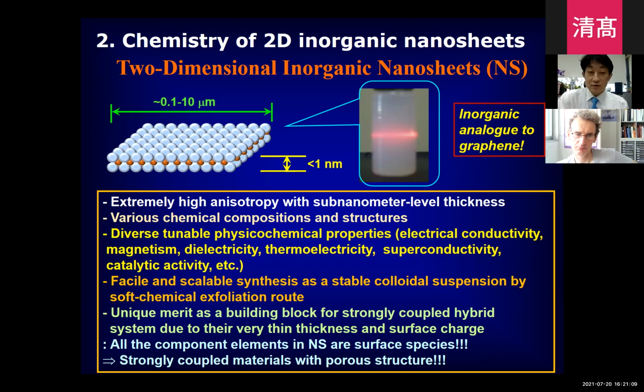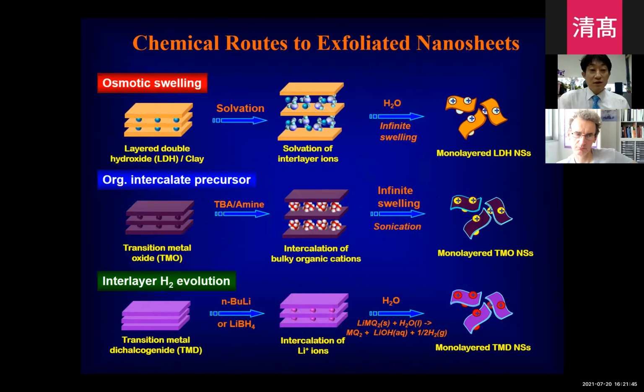When we apply those materials as building blocks to synthesize hybrid materials, due to the very thin thickness of these materials, all the component ions are surface exposed. So if you couple this 2D nanosheet with other nanostructured materials, we can get unusually strong electronic coupling. By using this material as a building block, we can get a very unique, strongly coupled hybrid material. In that way, we can get many valuable functionalities. Because we use those materials as building blocks, we focus more on the synthesis of monolayered inorganic nanosheets. There are three representative chemical routes to synthesize monolayered inorganic nanosheets.